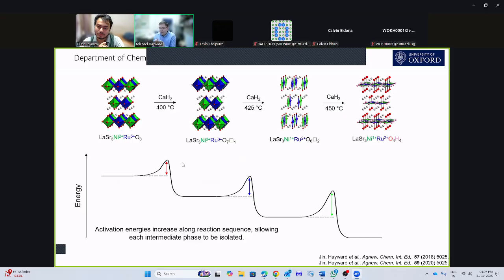Likewise, the O6 is a bit of O7 and a bit of O4H2. We can make pure O6 by going through the zirconium route, by having no hydrogen present. But trying to make O7 by this route is quite difficult. You always get a mixture. So this intermediate, I guess the point is that the barrier between O8 and O7 isn't so very different than the barrier from O7 to O6. So if you go over one, you always get a little bit going over the second one. So isolating the intermediates is quite difficult.